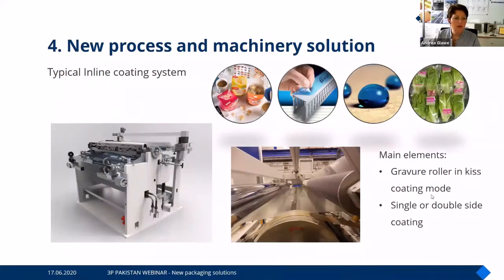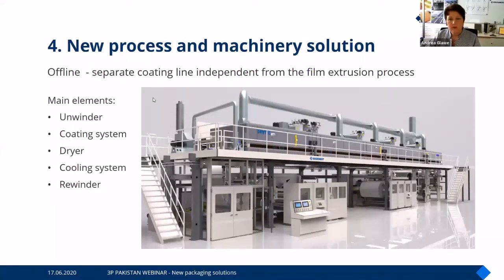The main elements are gravure roller in kiss coating mode, as you see here, and you can get that in single or double side coating application. When we go into offline, for sure, we need to handle the complete process. So we need an unwinder, which is in this position behind that enclosure. We have the coating system, depending on the process.